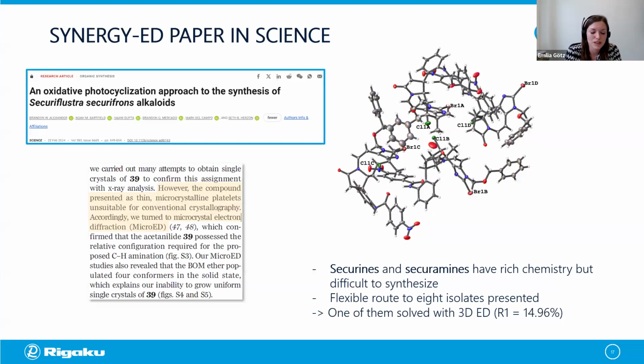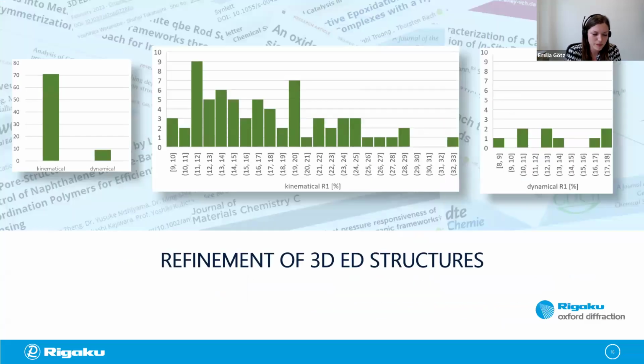So why do we have such relatively high R values for electron diffraction? One of the main reasons is that we tend to assume kinematical scattering, whereas for electron diffraction, we'd need to apply the dynamical approximation. And through these dynamical effects, the intensity of the diffraction spots are changed to a certain extent, and parameters that are looked at in single crystal X-ray diffraction kind of lose their meaning for electron diffraction. So a 2-digit R value doesn't mean we have bad data or that the structure is wrong. In fact, you can see here that most publications used kinematical refinement only and got R values in the 10 to 20% range for reasonable structure solutions. And a couple of them also refined with the dynamical approximation, which then led to generally lower R values.